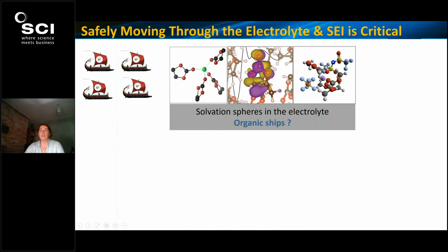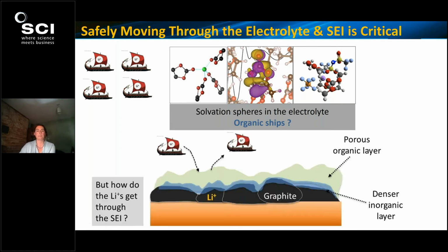And so in this central image here, you can see this little green circle. This is a lithium ion, and it's surrounded by a solvation sphere from various electrolyte components. And so we can kind of analogize these as being sort of protective organic ships, like you can see on the top left here, to convey the lithium ions safely to the surface or the shores of the graphite particles, which we can see here in a slightly simplified schematic. So we've got all of these solvation spheres dropping off lithium ions at the SEI port, where the SEI has a more compact inorganic and a more porous organic layer. So it's a kind of two-layer port, if you like.